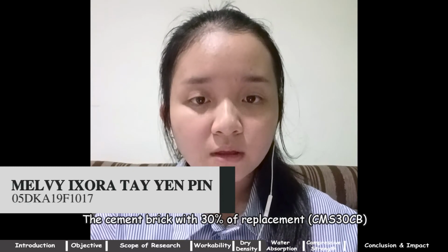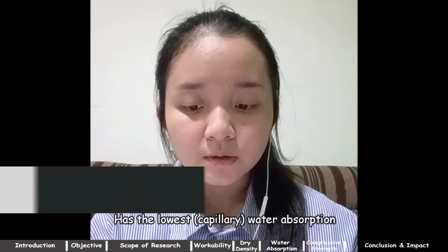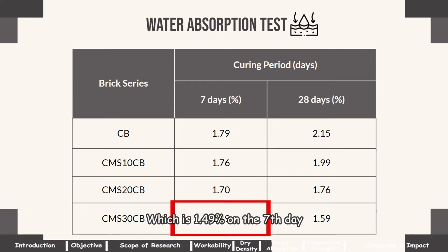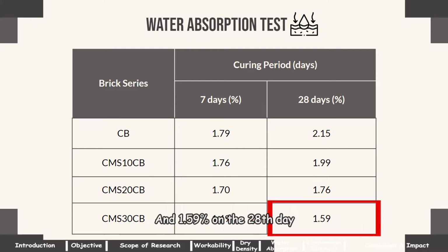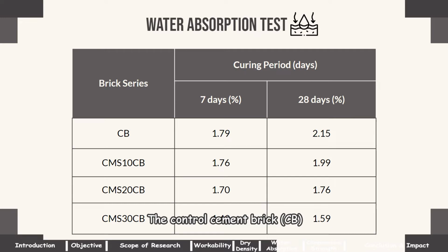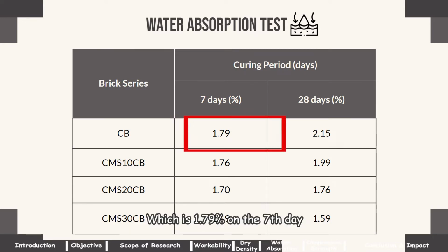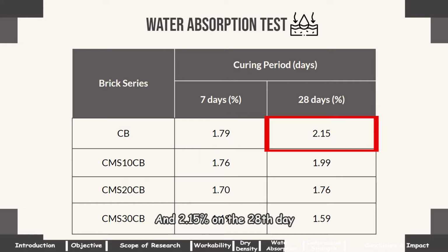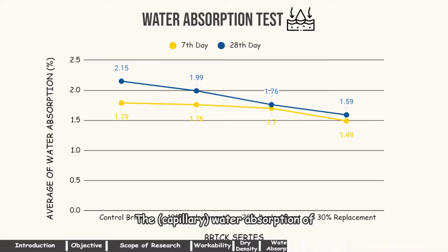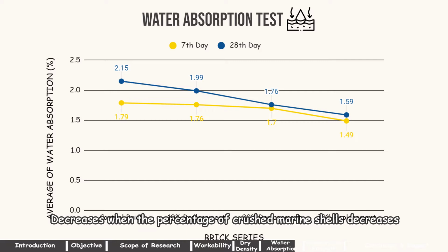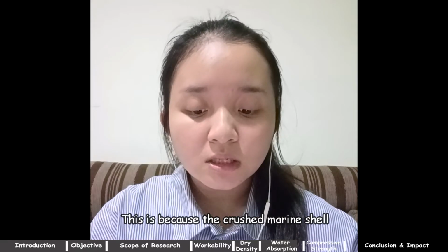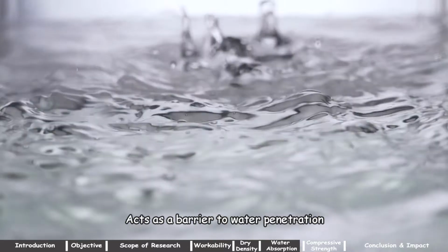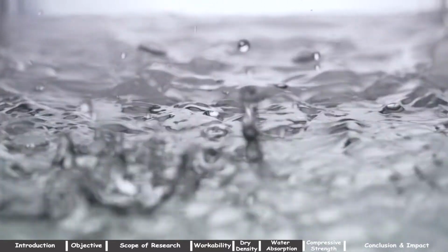The cement brick with 30% replacement has the lowest water absorption, which is 1.49% on the 7 days and 1.59% on the 28 days. The control cement brick has the highest water absorption, which is 1.79% on the 7 days and 2.15% on the 28 days. From the graph, the water absorption of the crushed marine shell cement brick decreased over the curing period, and it decreased when the percentage of crushed marine shells increased. This is because the crushed marine shell acts as a barrier to water penetration.